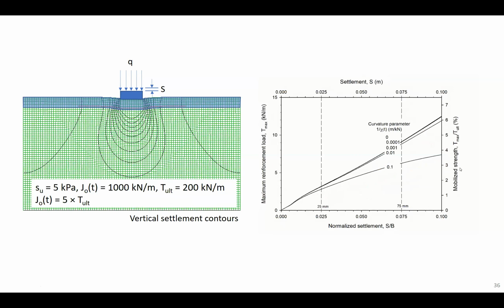And here again, we freeze the J0 parameter and just play around with the curvature parameter. So again, what you find is the loads in the reinforcement are less at every settlement level for the materials that are creepier than for the less creepy materials. And again, this doesn't surprise us.